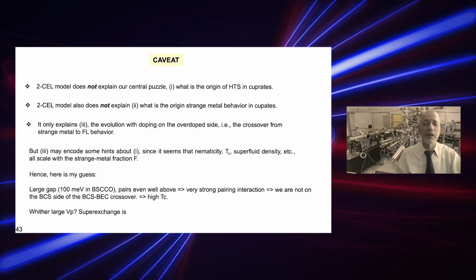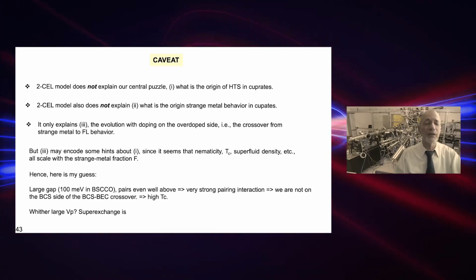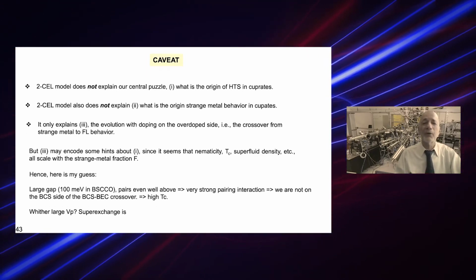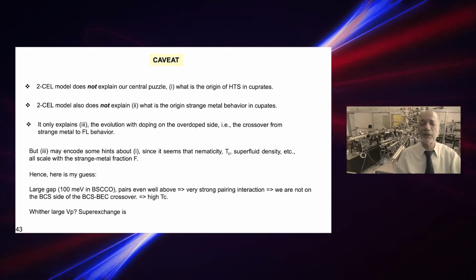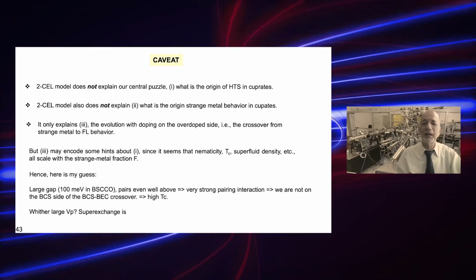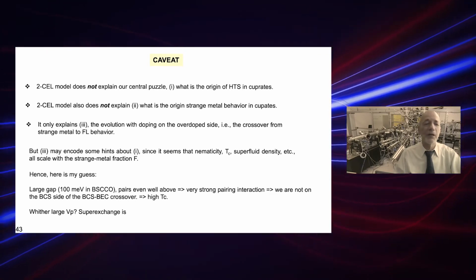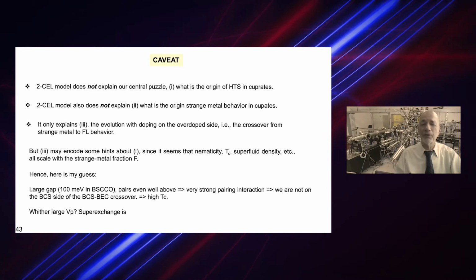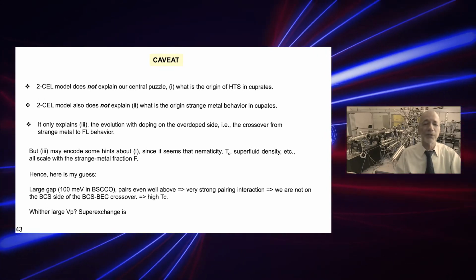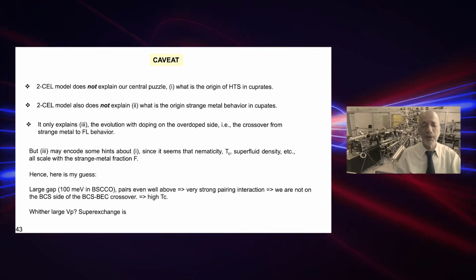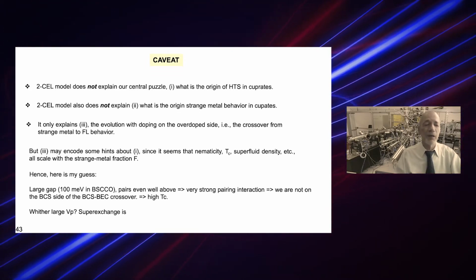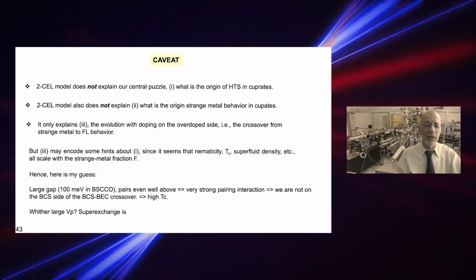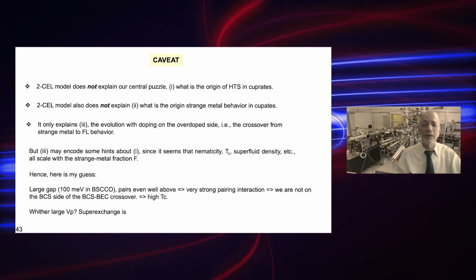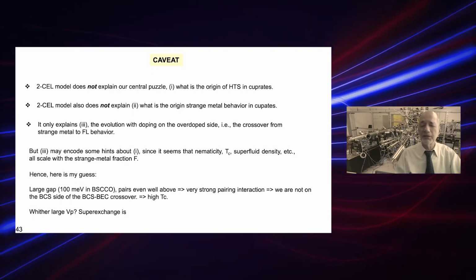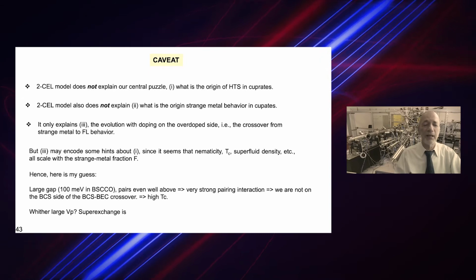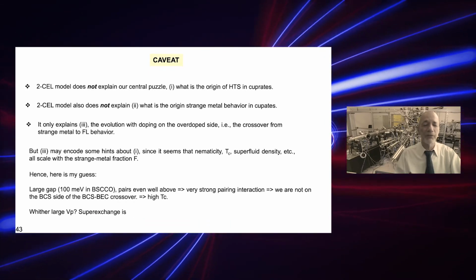Caveat here is that this two-component electron-liquid model does not explain our central puzzle, which is what is the origin of high-temperature superconductivity in cuprates. It also doesn't explain what is the origin of the strange metal behavior. It only explains the evolution with doping on the overdoped side, that is the crossover from the strange metal to the Fermi-liquid behavior, which may be specific to cuprates. But this fact 3 may encode some hints about 1, since it seems that nematicity, TC, superfluid density, etc., all scale with the strange metal fraction F.